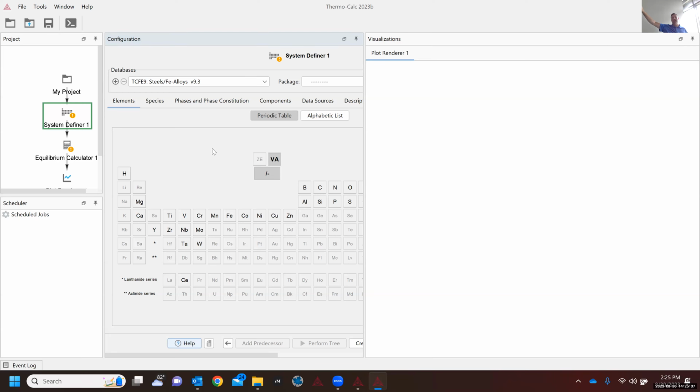So aluminum, cerium, copper, got several ternary intermetallics. We also put zinc in aluminum cerium alloys, or nickel in aluminum cerium alloys. So if you wanted to try to describe the thermodynamics of one of these aluminum cerium copper phases that's unique to the aluminum cerium copper phase diagram, and you wanted to describe how does nickel or zinc behave in that phase, you can't do it because that intermetallic phase is only found in that specific ternary system. And that's where nowadays we have DFT calculations. So for systems of interest, alloy elements of interest, people will do DFT calculations. They will calculate enthalpies of formation for these hypothetical intermetallics. And we can use that information now as input to improve our thermodynamic descriptions.